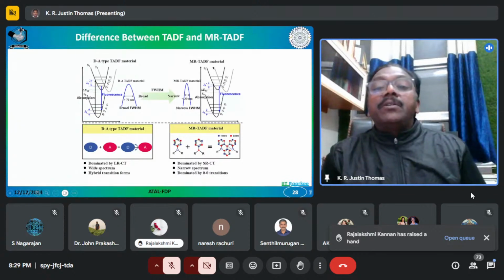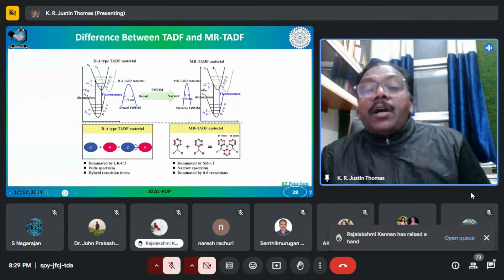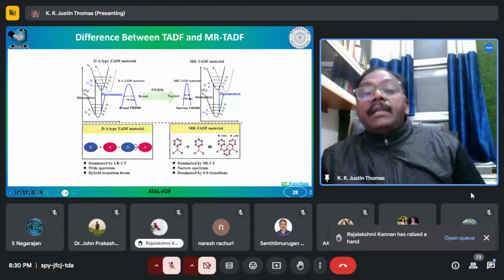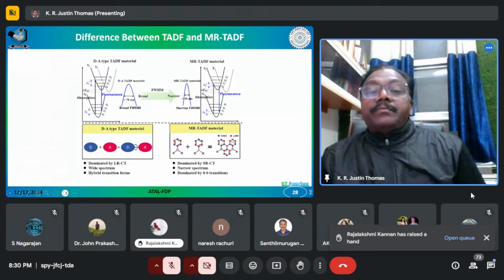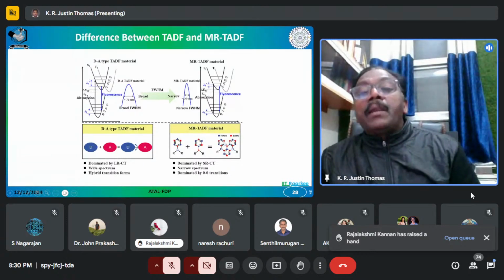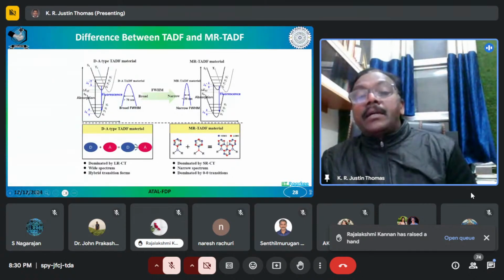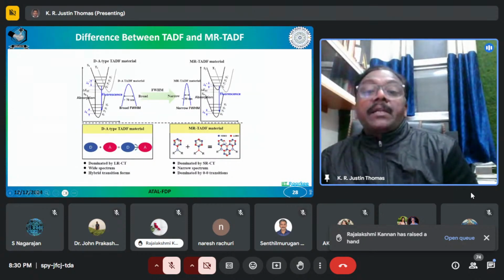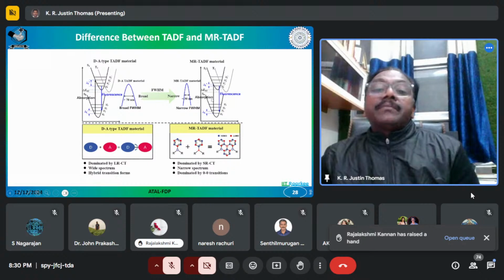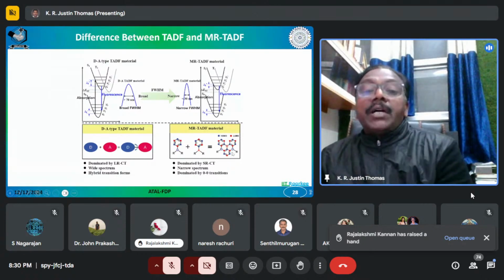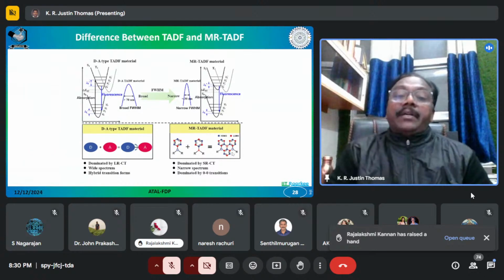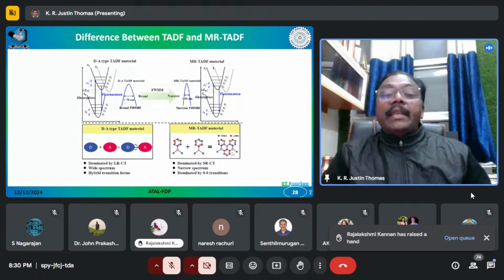There is no flexibility in the molecule. And then the molecular organization is in such a way that alternate atoms are donor and acceptor. For example, if you look at here, the red atoms are acceptor atoms and the blue atoms are donor atoms. So that means that the HOMO is predominantly on the blue atoms, that are the donor atoms, and the LUMO is predominantly on the red atoms, that are the acceptor atoms. And because of this short range charge transfer, atom to atom charge transfer, they lead to a very narrow spectrum.